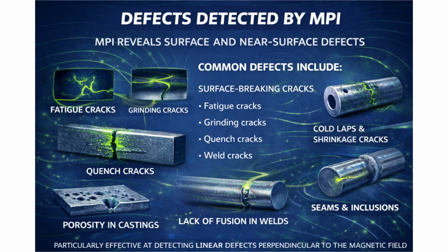MPI can also identify near-surface discontinuities, meaning defects that are slightly below the surface. Common defects include porosity in castings, cold laps and shrinkage cracks, lack of fusion in welds, seams and inclusions, forging laps and bursts. The method is particularly sensitive to linear defects that run perpendicular to the magnetic field. This is important because we'll need to adjust our magnetization technique based on what we're looking for.